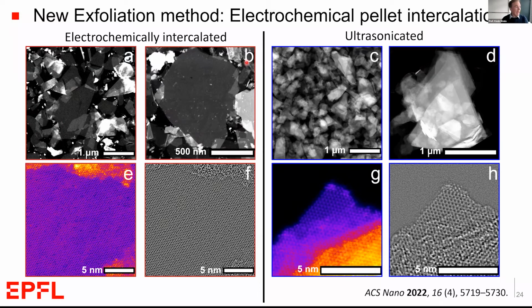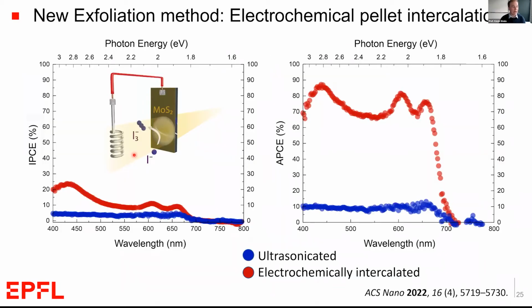And this new electrochemical intercalation approach means that we're able to achieve higher absorbed photon to current efficiencies compared to the ultrasonicated case. Now, I should note that in this data, this is a slightly different system, and we don't have any edge passivation on our flakes. But even without that, we're achieving quantum efficiencies now approaching 90%. So even better than the single crystal in this case. So we're quite excited about this new method to produce these nanoflakes, and hopefully we can also show this for solar-driven hydrogen production in the future.